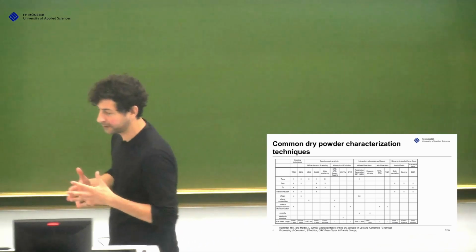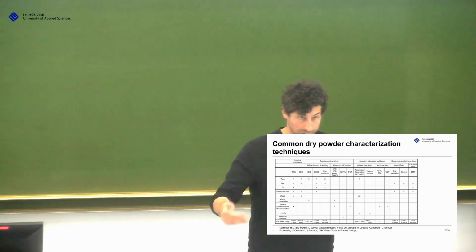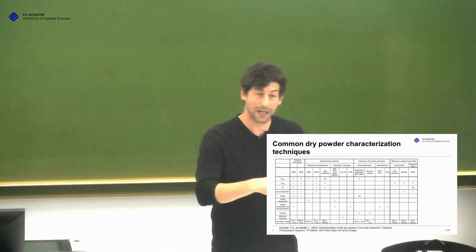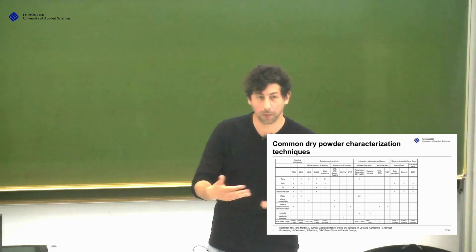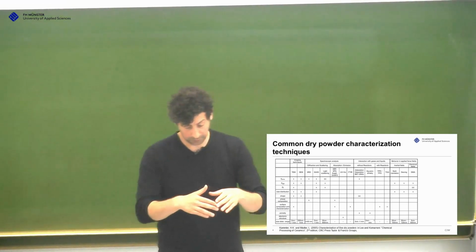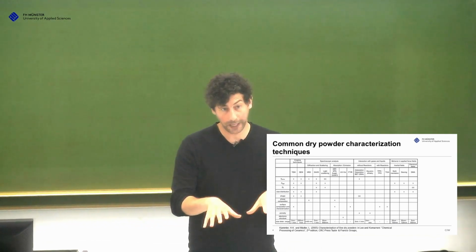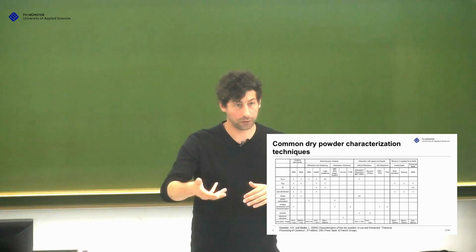So what I, for example, do is I take nanoparticles, I make an FTIR of my nanostructures, and then I know what is on the surface. And if it's very simple structures, I figure out the groups. In the simplest case, you have water and OH groups, and you know that water, which is basically physically bonded to the OH groups, leaves the surface much earlier than the OH group itself.